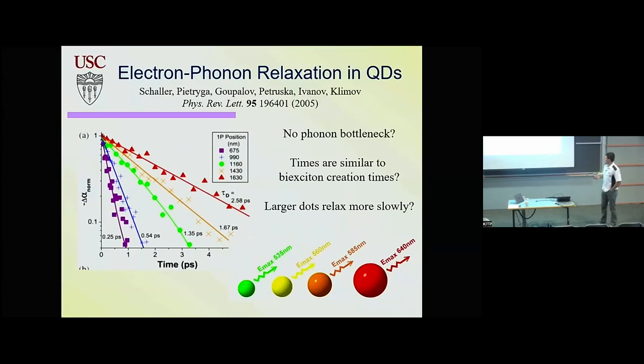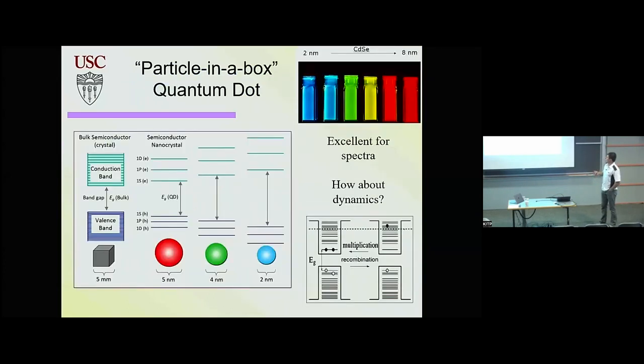So for example, if you look at this model, right, you would assume that if you make your dot smaller and smaller, you're going to open up energy gaps. And if you open up energy gaps, your losses to heat are going to slow down because these are heavy materials. And then heavy materials have low frequency vibrations. And then you have to make a transition across a fairly large electronic gap, you have to excite many phonons. So it has to be a multi-phonon process that's not very efficient. So if you reduce the quantum dot size, you should have slower relaxation.